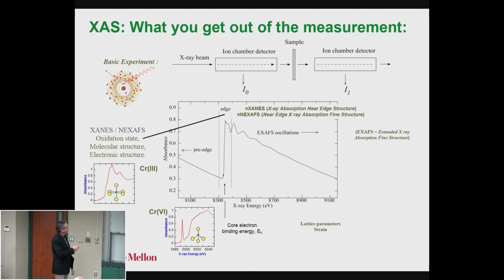Again, you have your X-ray beam coming in, it hits your sample, it absorbs, and then it will fluoresce off. And what you see, you're measuring absorbance as you're increasing the X-ray energy. So for a while, you get absolutely no absorbance, right? This pre-edge feature is kind of dropping down a little bit. And then for the element that you have, there's a specific energy where you're going to absorb a lot of energy quickly. And you can measure that.